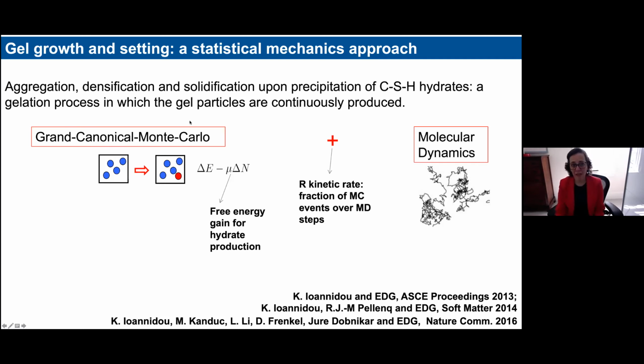And we combine this grand canonical Monte Carlo scheme with the molecular dynamics simulation, in which we can use the interactions that we know how to connect to the physical chemistry of the initial powder mix, to study how the precipitation of the nanoparticles interferes with the interaction of the nanoparticles in solution, and how this changes the way the gel forms.